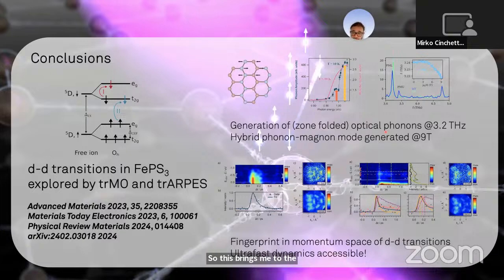I've shown you today our work on the iron PS3 and what happens when you excite these zero-dimensional atomic-like DD transitions in terms of generation of hybrid phonon-magnon mode, but also in terms of how this kind of transition evolved in time and how they decay again to the ground state, which is possible by performing time-resolved ARPES experiments. These results are published in these papers here, and the last part on the photoemission experiments is on the archive.